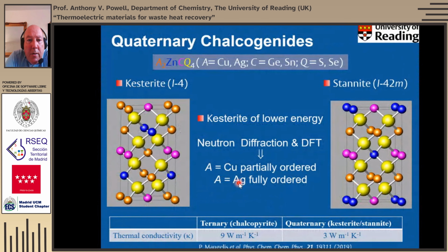So moving on from chalcopyrite, if we introduce not just 2 cations into the zinc blende structure, but we introduce 3, there are 2 principal possibilities, the kesterite and the stannite structure, which differ only in the way that the ions are ordered. So for instance, if this was an A site with copper in it, and the orange ones here are copper, in the kesterite structure, the copper is in every metal layer. In the stannite structure, they're restricted to 2 out of the 4 layers.